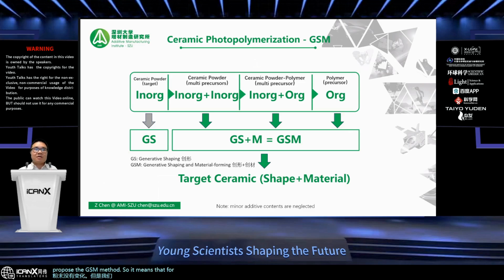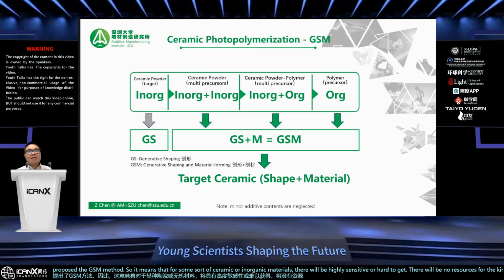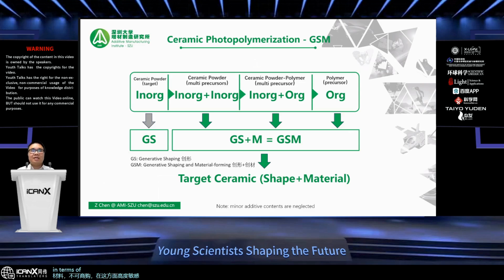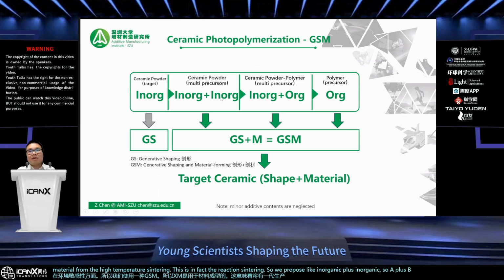So it means that for some ceramic or inorganic materials that are highly sensitive or hard to get, there will be no resources for that kind of material, and it is not commercially available. They are highly sensitive, in terms of environmental sensitivity. So we use GSM. In GSM, the M is for material forming. It means there will be generation of material from high temperature sintering. This is in fact reaction sintering. So we propose inorganic plus inorganic, A plus B, both inorganic materials, or one can be inorganic and another one organic. The last one is they can be entirely organic.